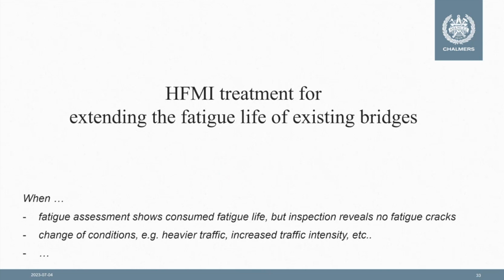A couple of slides on the use of HFMI treatment for extending the fatigue life of existing bridges. This could typically be the case when we do fatigue assessments of existing bridges. The calculations show that the fatigue life is totally consumed, but inspection reveals no fatigue cracks. Or when we have bridges that have been in service and a change of conditions, for example allowing heavier traffic or increasing the traffic intensity, results in shortening the design fatigue life, and there is a need to extend the fatigue life.